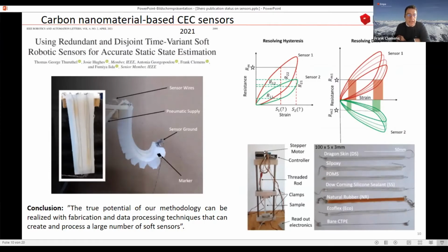We first thought, okay, this is a bad behavior, so we have to avoid it. However, Thomas found a way and said, wait a minute, we can use these bad materials to build up a system where we have different kinds of sensors. So you see here sensor 1 and sensor 2. And by the different behaviors of sensor 1 and sensor 2, we can neglect the drift and the relaxation, and by using a neural network approach, we can then read out the right sensor data which we need for the application.